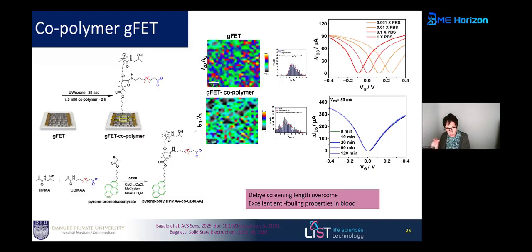But let's go to the things which are important for us. It's the Debye screening and the anti-fouling properties. So what you see here is that we keep extremely nicely the gFET characteristics in different ionic strengths. But when you leave this type of sensor for up to 120 minutes in full unprocessed blood, the signal is not changing. So we hope to have overcome both problems, the Debye screening and the anti-fouling.